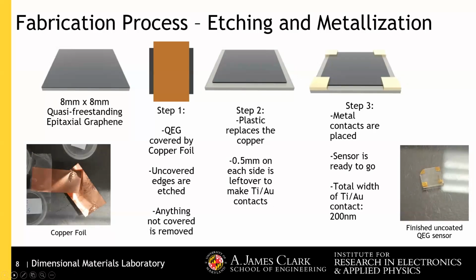Etching, it sounds complicated, but I'll explain it very simply. First, we take our sensor and cover it with copper foil. The copper foil leaves about 0.5 millimeters exposed on each side. From there, we do etching, which rips off the edge of the graphene that's not covered. Then our sensor looks like this, with the graphene at the top and the substrate at the bottom, the exposed center.